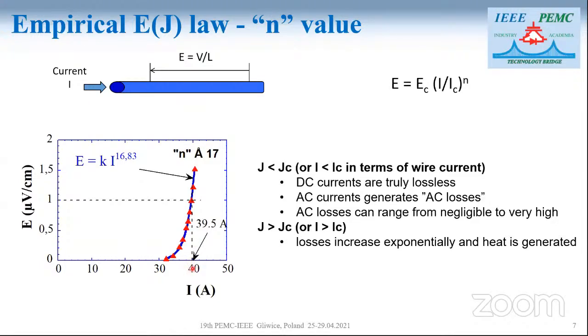It is the current for which the electric field value is 1 microvolt per centimeter. As you can see, the critical value of the current in this sample is about 40 amps, because at this point you have the critical value of the electric field, which is defined by a normalization of 1 microvolt per centimeter. If J is below Jc, you can transport the current without losses. But if we use AC current, you can generate losses, and these losses can range from negligible to very, very high. That depends on the frequency and on the conductors. If J is superior to Jc, losses increase exponentially, and heat is generated, and you can destroy your sample or your coil if it is a coil.